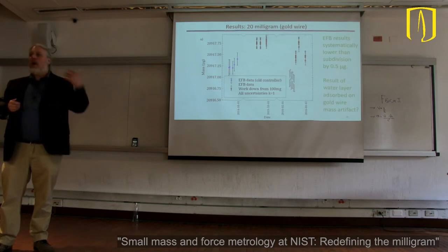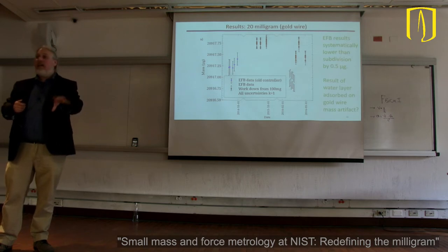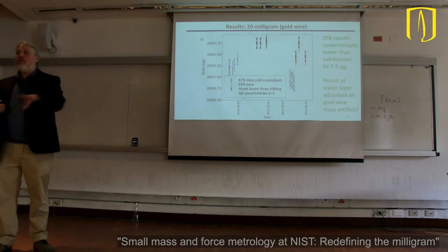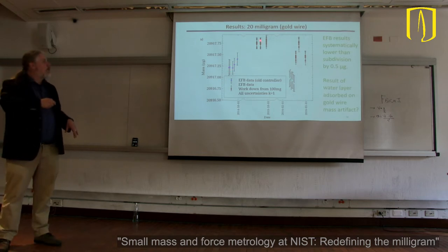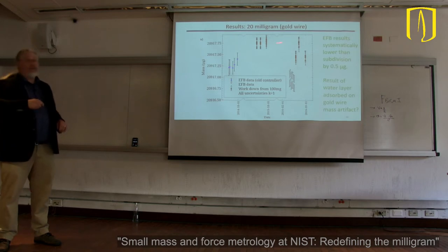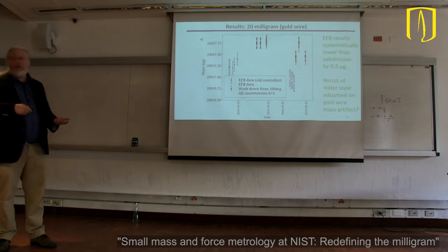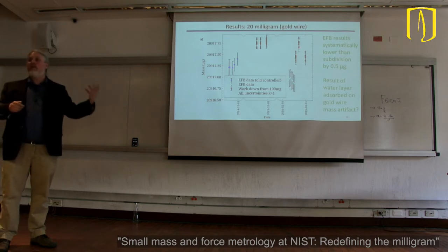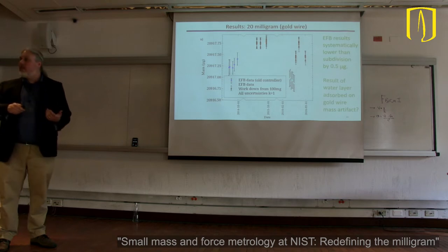Water will absorb on the surface of the mass. And depending on the humidity, the amount of water that absorbs on the mass will change. Our measurements are in vacuum. The measurements from the subdivision method are in air. At first, we thought, oh boy, we have another problem. But then we realized, well, probably what's happened is the water is desorbing in vacuum. So we should hopefully expect to see something like that.